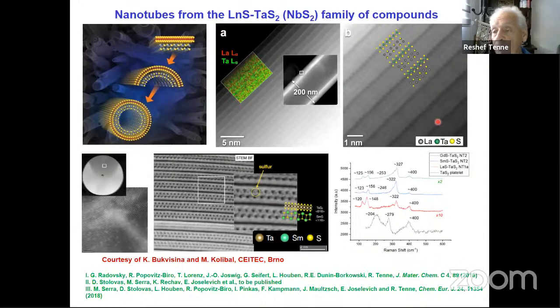You can superimpose the calculated structure on the nanotube. This is the nanotube. And we can make sections. We can actually cut these nanotubes now very nicely with FIB, and we can see the sections. This is a high resolution image of a section that was built. It's like a coin from the nanotubes. You see that it's a multi-layer structure, and you see beautifully the atoms of the samarium and the sulfur. Here you don't see clearly the tantalum, but the black line is basically tantalum.